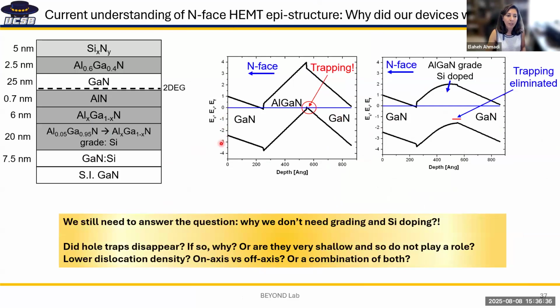Now, the question going back is, why don't we need silicon doping and grading? That's something we are putting more focus on to understand, because the whole purpose of having this in nitrogen polar, our current understanding is that if we just do this AlGaN barrier, the valence band gets close to the Fermi level, and there are hole traps here that the untrapping of these hole traps leads to dispersion. And the reason for grading and silicon doping is to push down the valence band, and the trapping is eliminated.